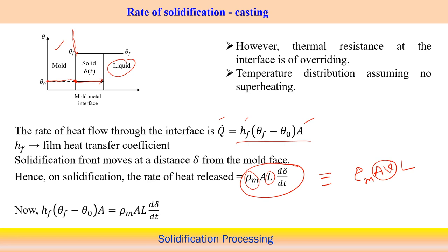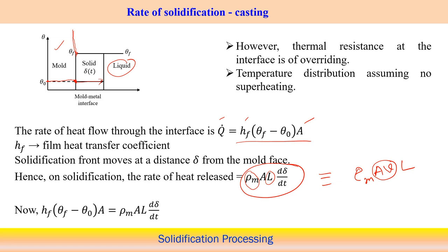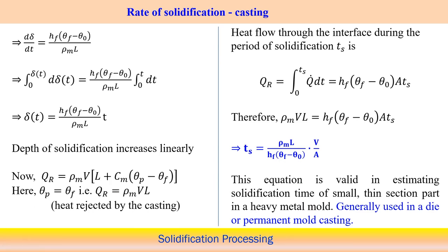Now in these two cases, from one point of view we are considering the interface resistance, and based on that, what is the heat flow at the interface. In the other case we are considering the amount of heat released to make the solidification front move over the distance delta. So we make these two equal, or I can say that in the steady state situation this must be balanced. Here HF theta F minus theta 0 is the total heat flow through the interface, and in the other case there is the rate of heat release through the movement of the solidification front. So we make them equal, and we reach this equation: d delta by dt equal to HF theta F minus theta 0 by rho m into L. This expression we can reach.